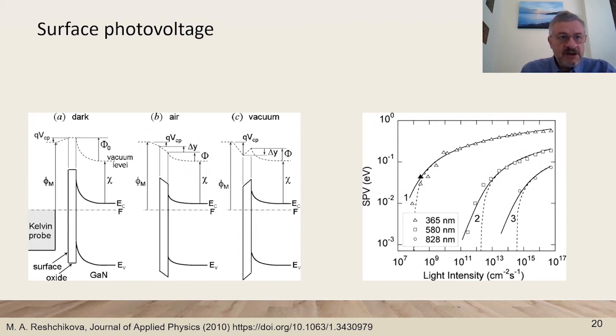So here we can see several examples of applying the Kelvin probe to a given semiconductor with a surface oxide layer. So here is the initial contact potential difference, which is the difference of vacuum level between the sample and the probe. And when we change the medium, this is going to change, so that we can see that we are going to modify the contact potential difference in different cases, so we know which is the state of the surface. Then by applying illumination, we can track the surface photovoltage in different situations.